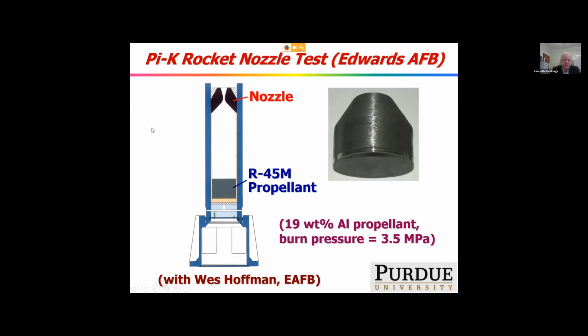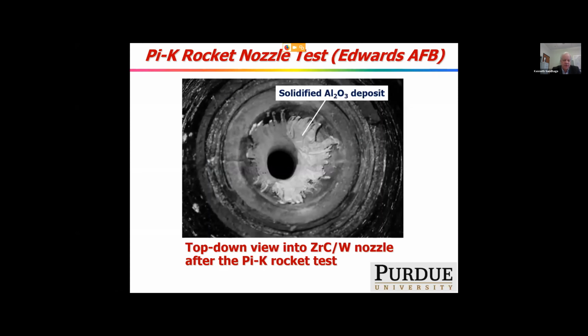And then he conducted the test using an R45M propellant, a Pi K rocket test. It has a fairly high aluminum content, so it's fairly erosive. And when Wes pulled it off, he saw no evidence of erosion from this material. And so this is a very thermal shock resistant, erosion resistant ceramic that survives that kind of an extreme condition.